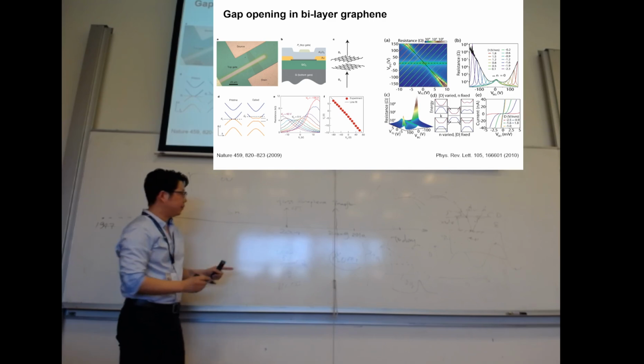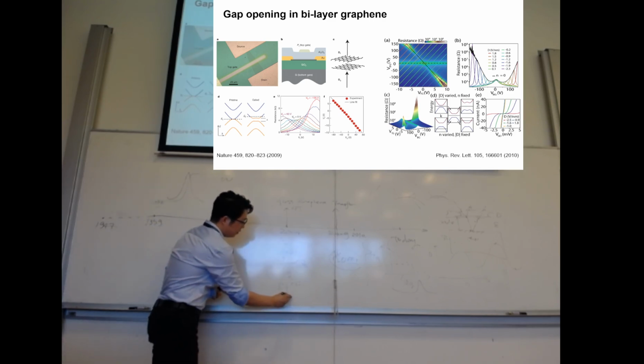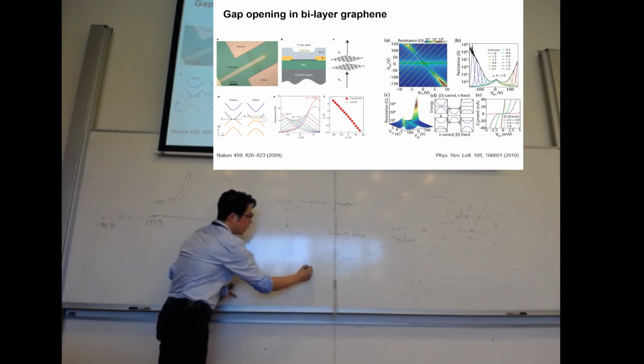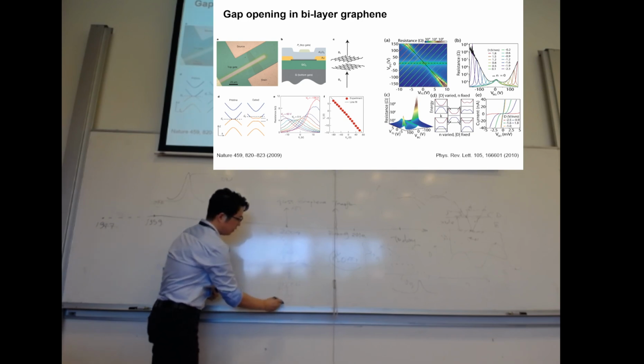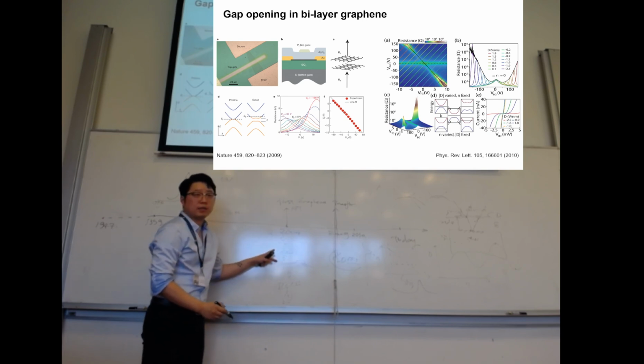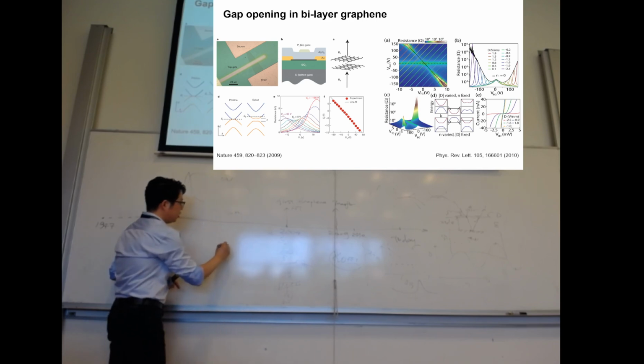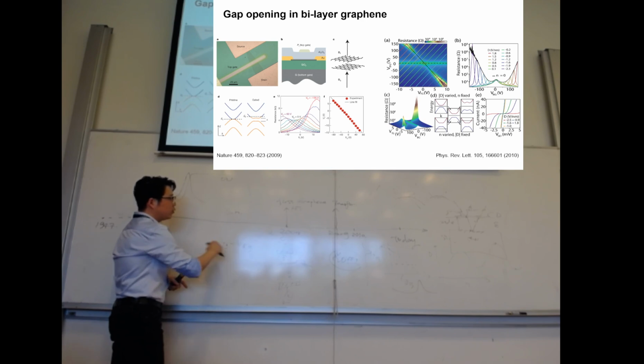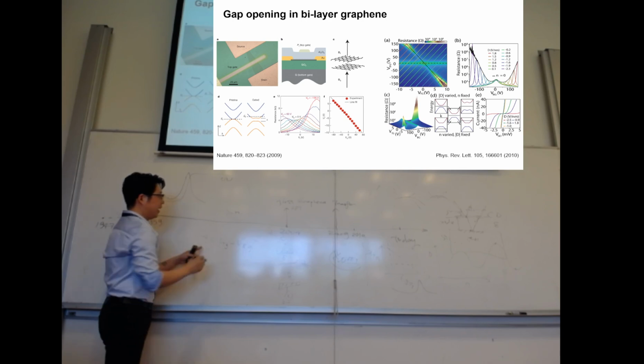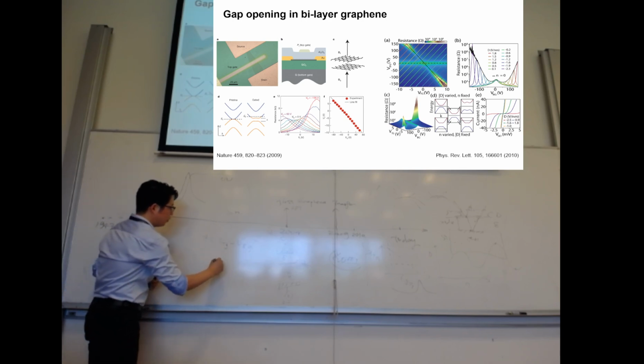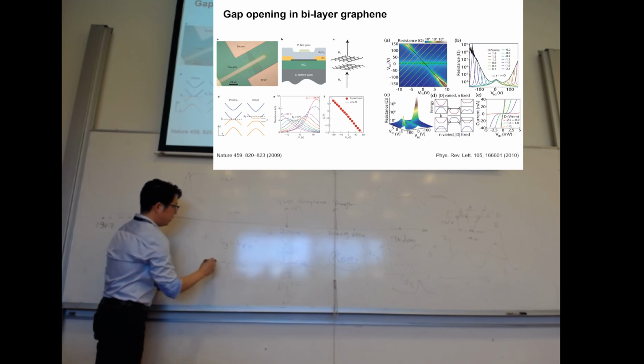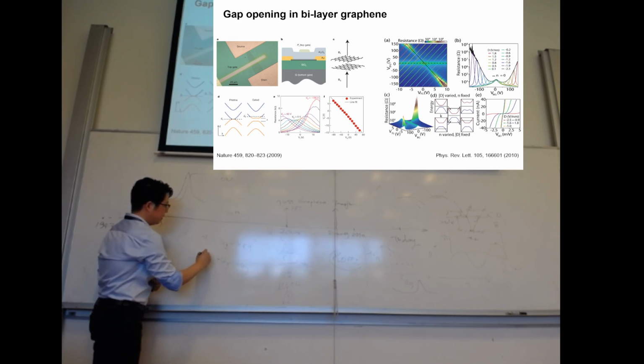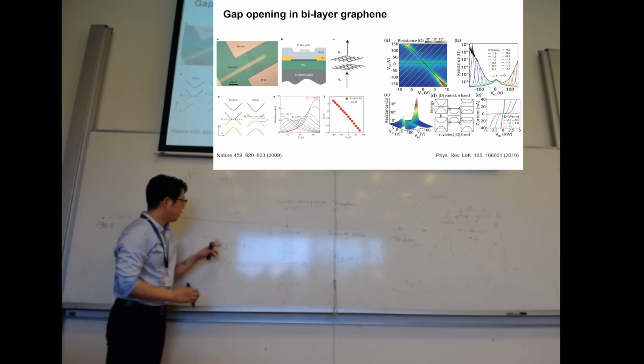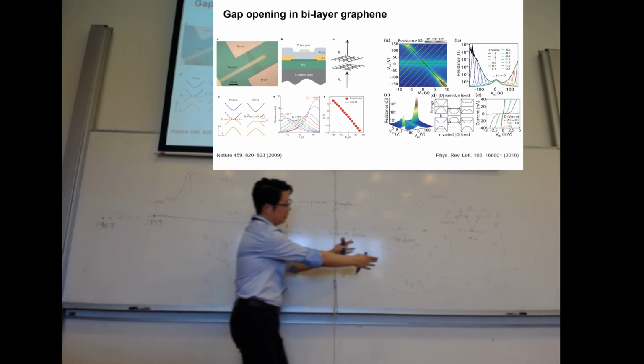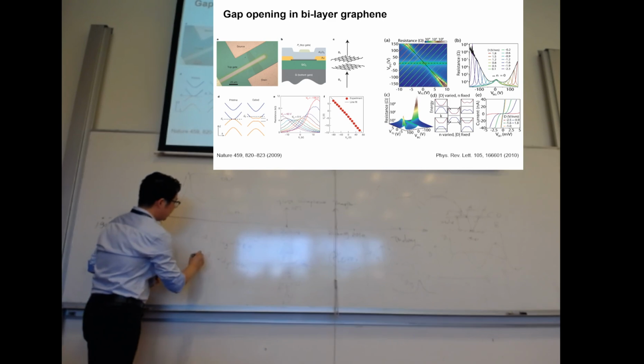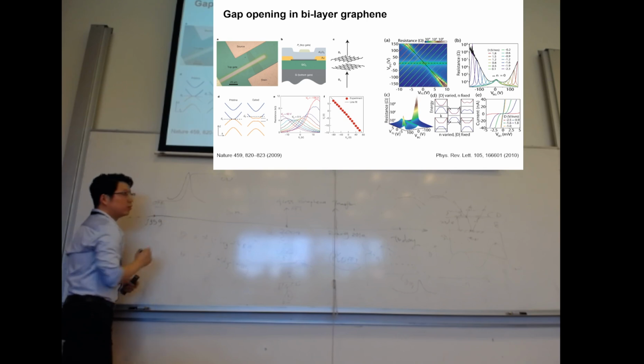That's the experimental setup. You have a voltage here, a voltage there, which is with respect to the ground, and they are self-grounded also to have this potential applied. You basically have two capacitors there. And if you use VTG minus VBG, the two signs give you a definition of electrical field, with some kind of a parameter for that. And if you use VTG plus VBG, there is some prefix there, let's forget about that. There's a beta. If the two are identical, then it's just one. Otherwise the ratio is slightly different. So this one defines the carrier density, this one defines the electrical field.